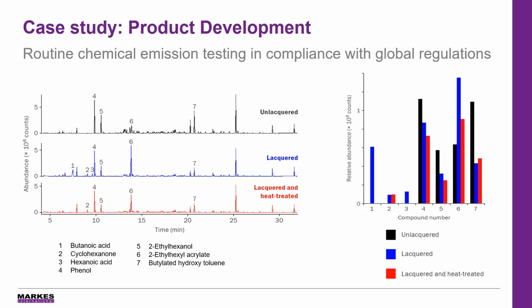2-ethyl hexyl acrylate. So the third sample that was tested was the flooring sample that had been lacquered and then subsequently been heat treated. And during that heat treatment, there was the reduction of phenol and the BHT, which were needed to bring it in line with the regulation, and also a reduction of that butanoic acid and the ethyl hexyl acrylate. So that allowed the sample to then fall within the relevant regulation limits. And this is where the microchamber is great. All these different samples taken from the production line, and then they can be sampled simultaneously from the microchamber over a relatively short period of time.